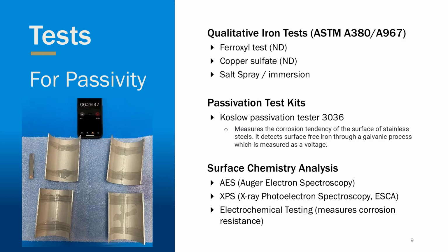Now the Koslow tester, I have that in the middle. That's a pretty popular device. It's semi-quantitative, I say, because it measures the actual reaction potential, but it is still just measuring the residual iron. You aren't really measuring the passive layer. You're just measuring if any iron was present on the surface, and if the reaction proceeds, then you're in a certain millivolt range for your reaction.